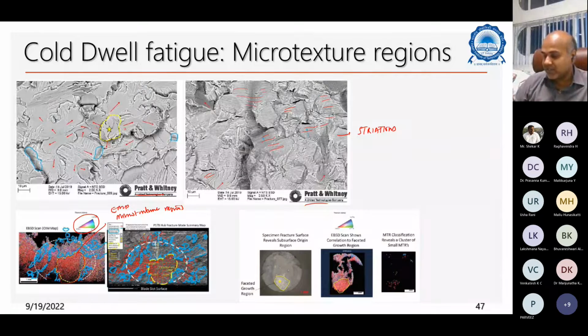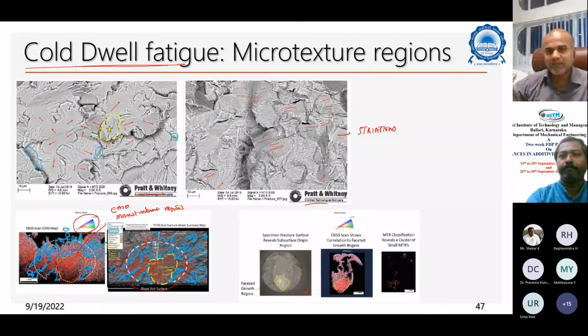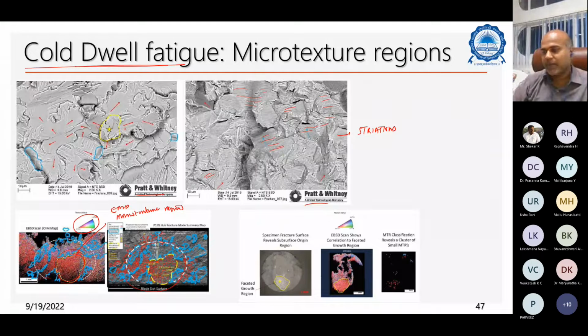So what they found is that these are the regions where the alpha prime, or one particular phase, is getting dominated, and that these microtexture regions are responsible. They started with some microstructure in the beginning as a wrought processed one, and then during the fatigue cycle, because of a lot of texturing and coagulation of a single phase during the material transformation, it led to this kind of abrupt failure. This is called cold dwell fatigue, because the material goes from high temperature to low temperature subsequently, which leads to microtexture regions. These microtexture regions are the reasons for the premature failure of the material, the engine or hub.